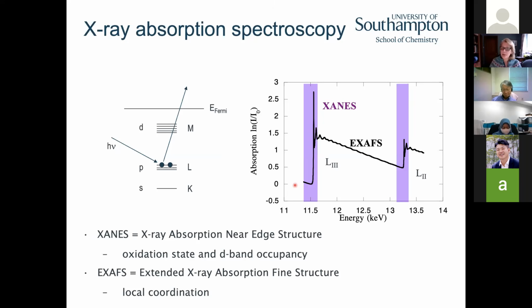So X-ray absorption spectroscopy, this is a core electron spectroscopy. So here if we're at the L edges, for say platinum, we're exciting the P electrons in the core, the 2P electrons. The X-ray energy is scanned until this transition occurs. And the electron then leaves the absorber, the absorbing atom, and is promoted to above the Fermi level. So it leaves the atom and goes out, it's going to interact with the surrounding atoms.